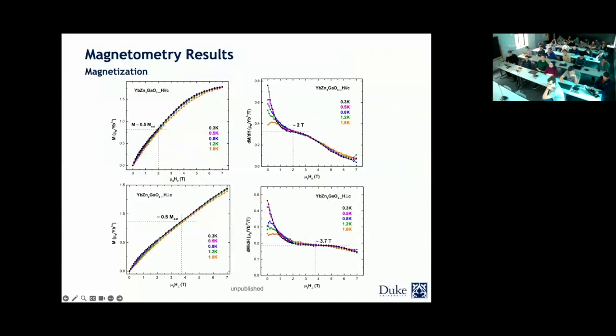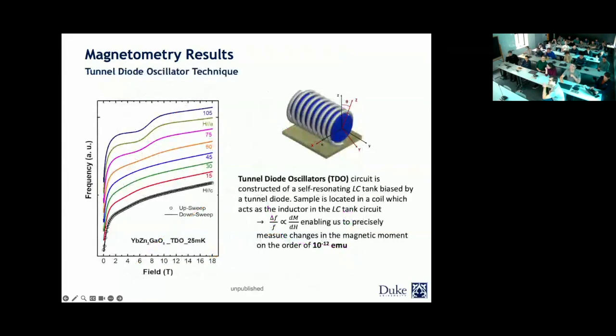In this case, we are seeing it actually happening at half of the saturation, which is again another indication that there is more that still needs to be understood in this particular case. To be able to do this at a higher resolution, we actually went back to MagLab and did this measurement. This is called the tunnel diode oscillator technique.